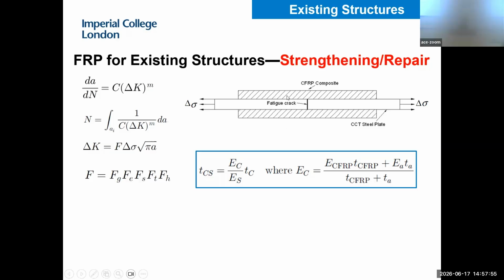If you can convert this FRP material into equivalent steel, that means you increase the steel thickness. Then you can calculate the new stress at the crack, and use the classical steel design strategy—you can keep using the same steel design standard. So this is how we did it.